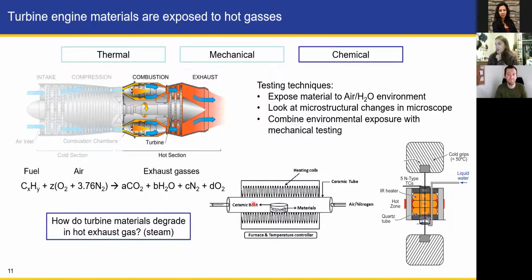So what I do is I use a tube furnace where I put my material in a ceramic tube on a plate, and I introduce air or water vapor into my materials, and I can control temperature with these heating coils. And then I use a microscope to look at the changes of the microstructure before and after exposure.